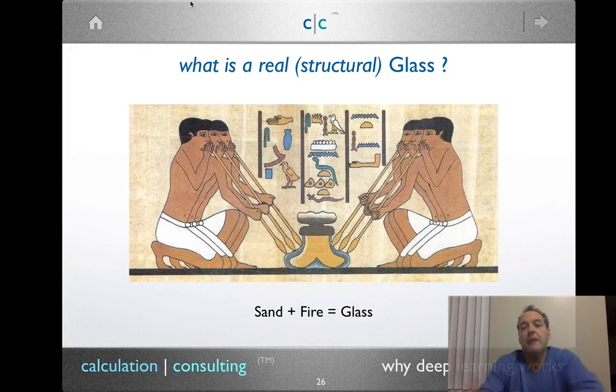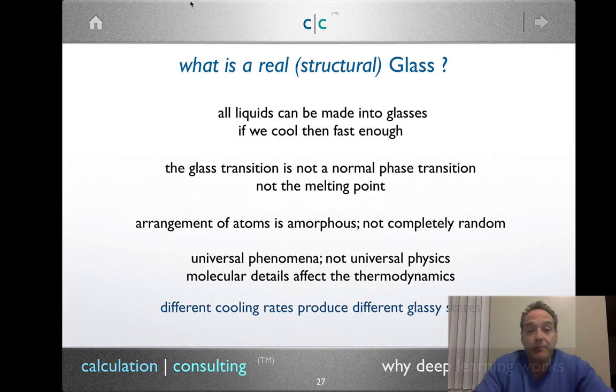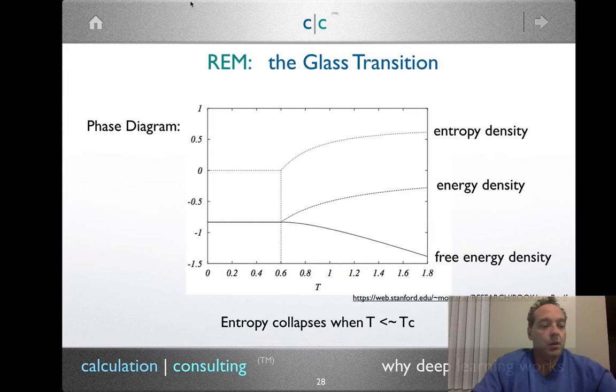the Egyptians blowing. When you go to a glass blower and they blow a glass, they change the way it cooled. Part of the glass can be made to be brittle. Part of it's brittle and will break, and other parts are very hard. And the ancient art of glass blowing relies upon this very simple fact that different cooling rates produce different glassy states. So when we think about the glass transition, we can introduce a phase diagram.